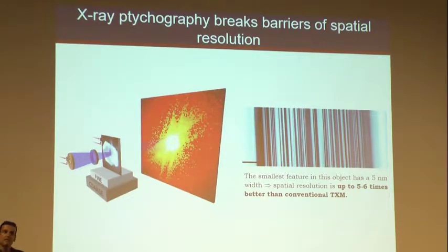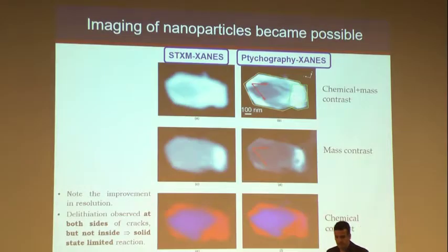But the idea here is that for us, it was a way of doing a measurement at spatial resolutions below 30 nanometers. Their initial measurements gave them 5 nanometer spatial resolution with an ideal object. I believe that they can do 3 now. The question was, what happens now when you're trying to do chemistry? And so they came to us asking for objects to study, and so we gave them one of the lithium iron phosphate particles or samples that we had. Same idea, it's only partially dilithiated, so it has both the iron 2 species and the iron 3 species. And we were trying to see if we could map it within a particle.